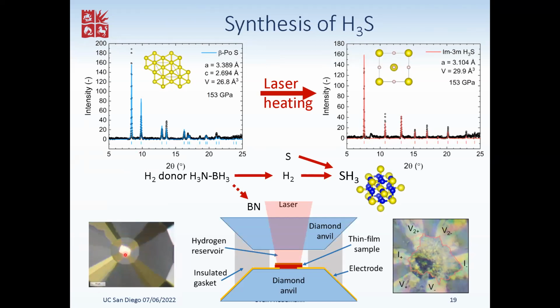You can see here at ambient pressure the nice yellow piece of sulfur sitting on top of the electrodes. We then prepare gasket and anvils and everything, and we load the gasket space with a hydrogen donor material. We've not used elemental hydrogen because that's quite tricky to deal with. To get a sensible density of hydrogen in a diamond anvil cell, you need to put the whole pressure cell into a hydrogen loading system where you pre-compress to 2000 bar.